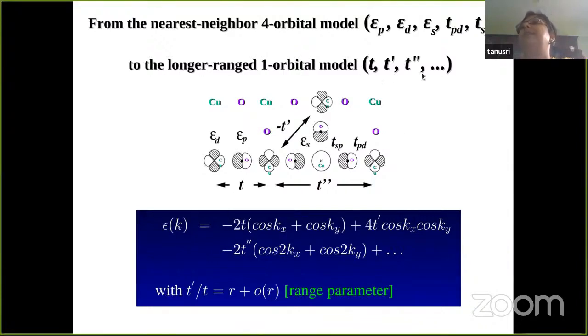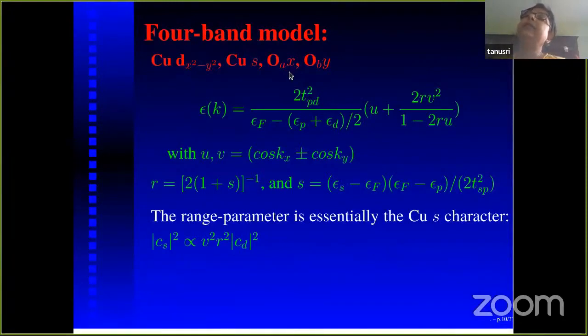long-ranged 1-band model, which consists of t, t prime, t double prime. And you can define a range parameter, the same R parameter which we have seen before, in the sense that this R is now a ratio of t prime by t, and all the other long-range interactions like t double prime and so on and so forth are basically various powers of this R. And with the detailed calculation, you can actually show this range parameter R of this one-band model essentially depends on the energy position of this s orbital.